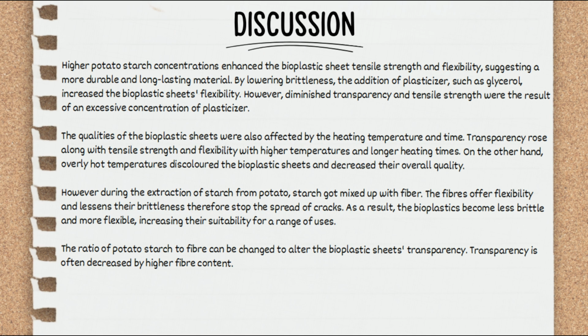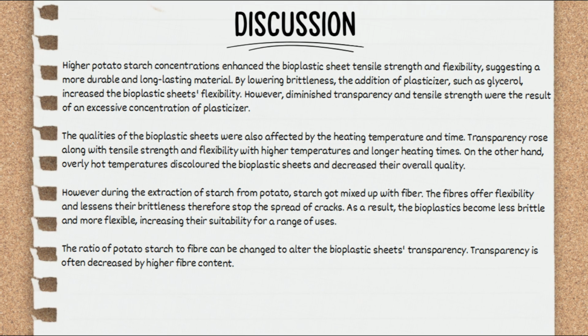However, during the extraction of starch from potato, starch got mixed up with fiber. The fibers offer flexibility and lessen brittleness, therefore stopping the spread of cracks. As a result, bioplastic became less brittle and more flexible, increasing its suitability for a range of uses. The ratio of potato starch to fiber can be changed to alter the bioplastic sheet's transparency. Transparency is often decreased by higher fiber content.